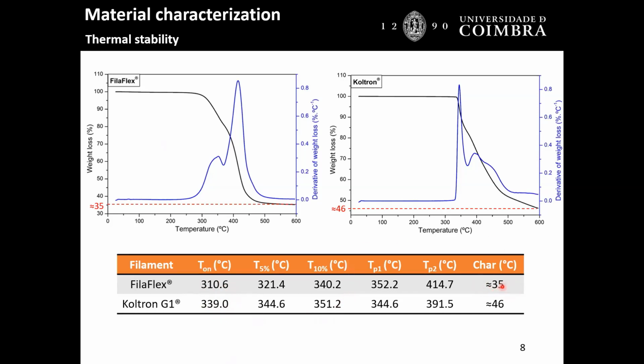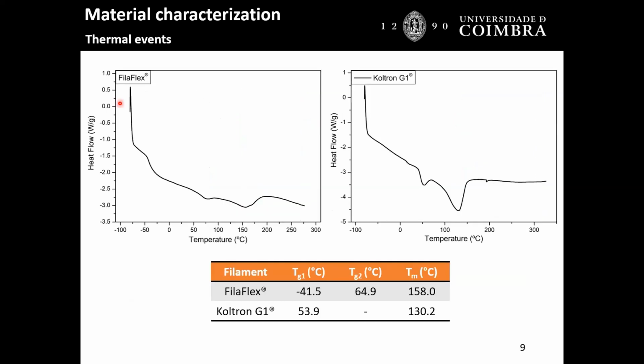Also, we saw that we have 35% of char for Filaflex and 46% for Coltron. When we compare this percentage of char with those of the TPU and the PVDF non-composite materials, so the thermoplastic materials, we know that we have more or less 15% of reinforcement in weight for Filaflex and 30% for Coltron. Okay? Well, another characterization was DSC, and we saw that they were semi-crystalline, and the Tg and the Tm of both were determined, once again to define the temperatures at which we should process the polymers.